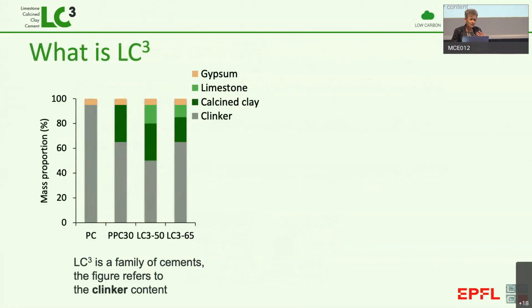And what's interesting about this LC3 is that by putting the calcined clay together with limestone, we can go to much higher levels of substitution. So this would be the composition of, say, a cement including fly ash. You would have about 70% of the Portland cement and about 30% fly ash.